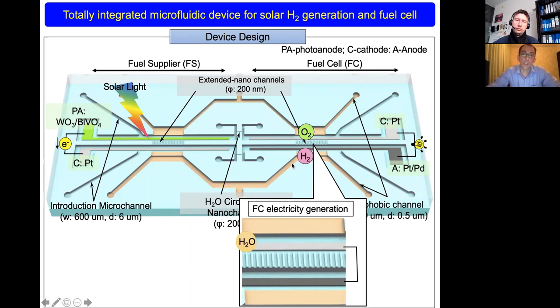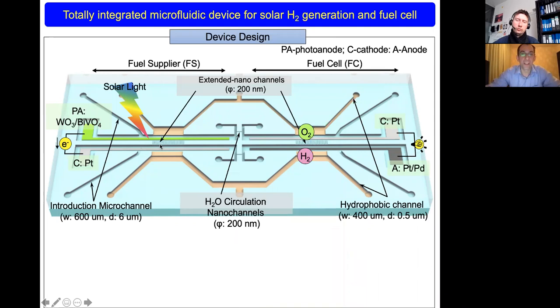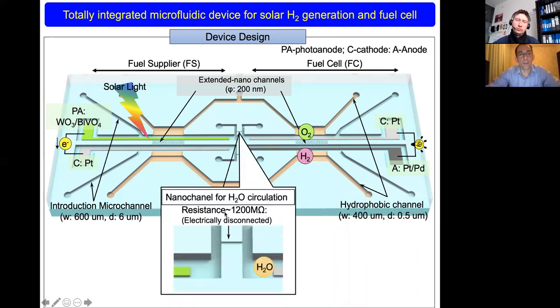Of course, here we have overpressure, because if you generate a lot of electricity from the hydrogen and oxygen, then water is produced. Then we need to return water to this device, because here is water splitting. So for this purpose the nanochannel was designed, and we measured the resistance of this nanochannel, and it's very, very big, around 1,200 megaohm. That means that these two devices are electrically disconnected. However, physically they are connected. Okay, and the water comes here.